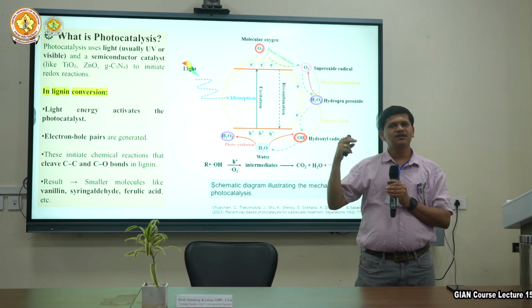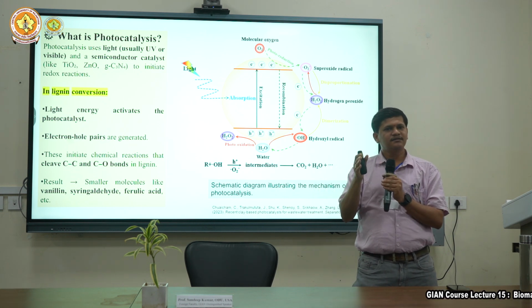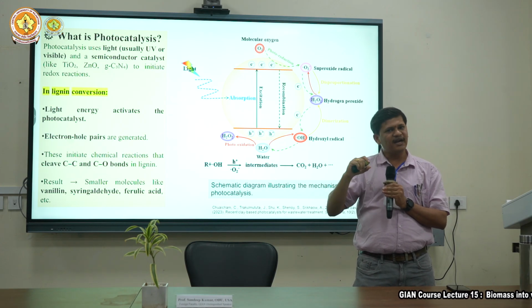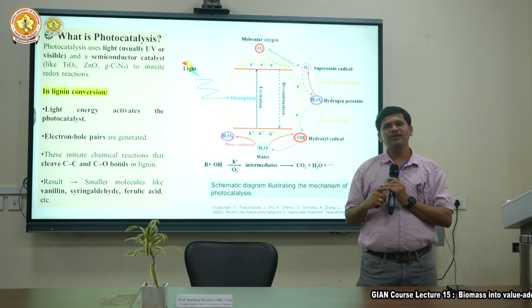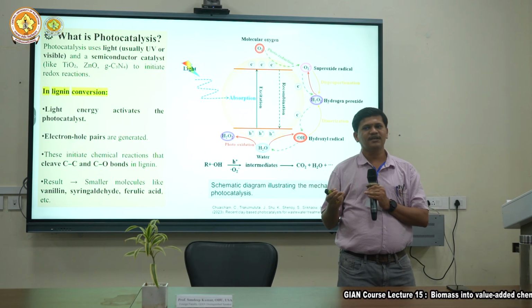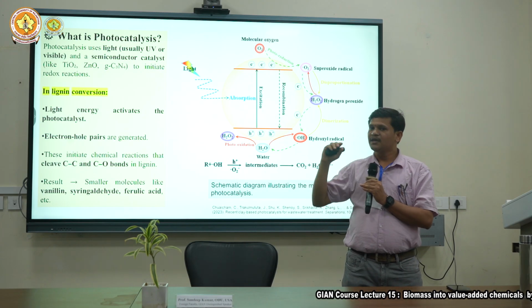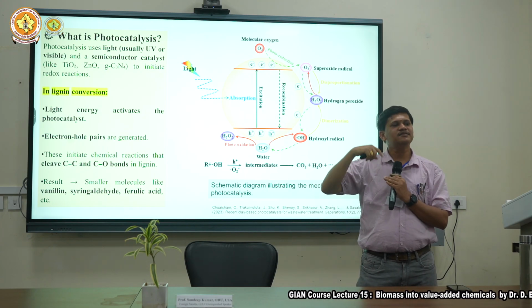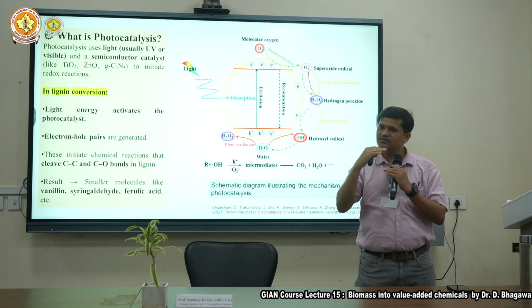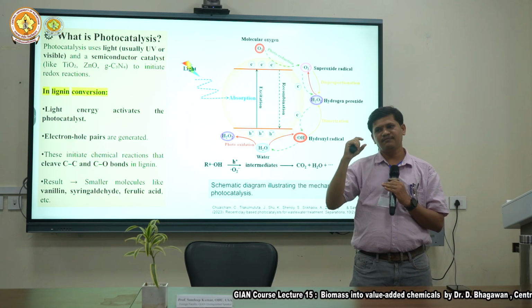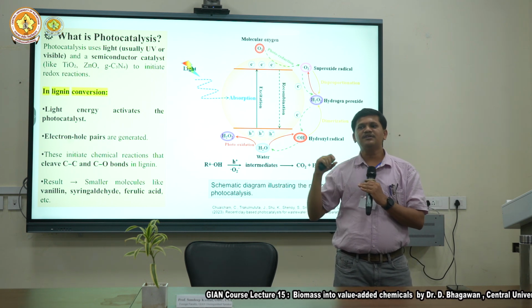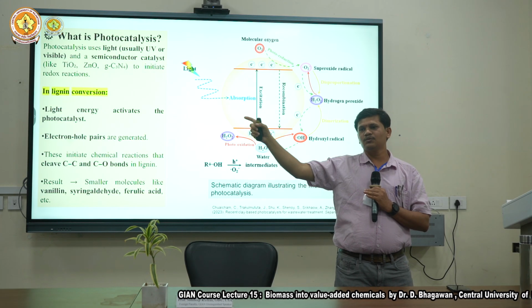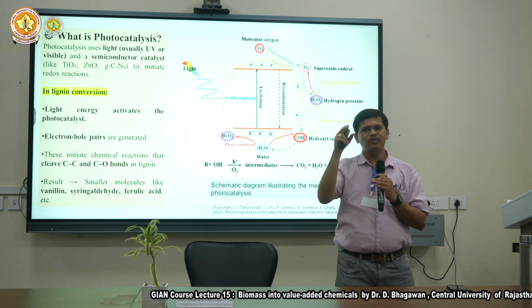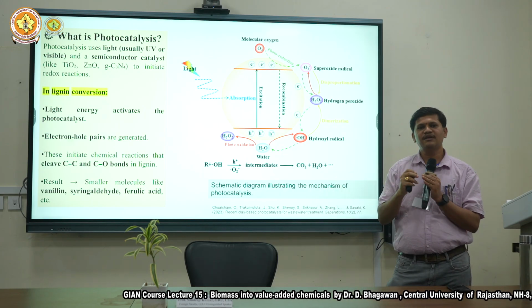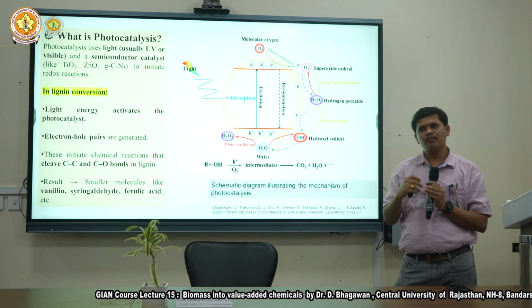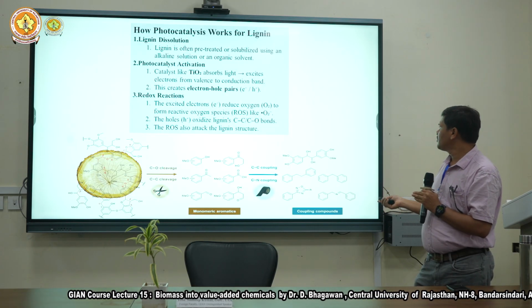During the synthesis process, we can dope this with any other semiconducting material which has a lower band gap compared with zinc oxide, and the second option is doping this zinc oxide with a conductive material. By that way we can enhance the transformation of electrons, because whenever the band gap increases, the transfer of electrons will consume some energy. So if you reduce this band gap, then you can save the electron energy which was generated. So that energy can be used to cut down the lignin compound. So while designing the experiment, we need to see which chemical compound, which heterojunction can help us. If we decide that, then we can move on.